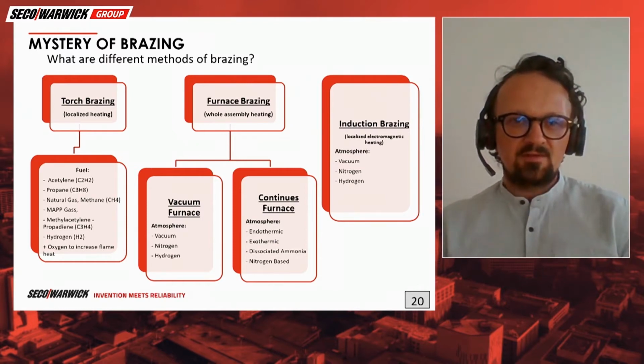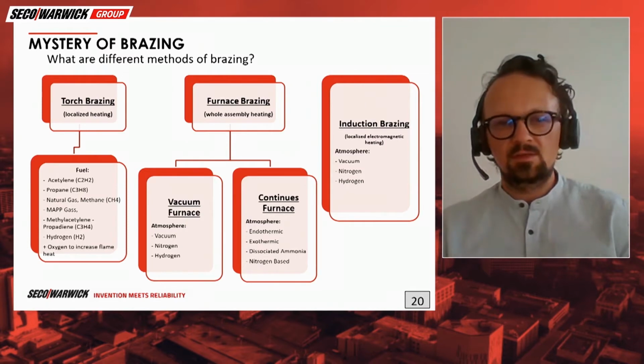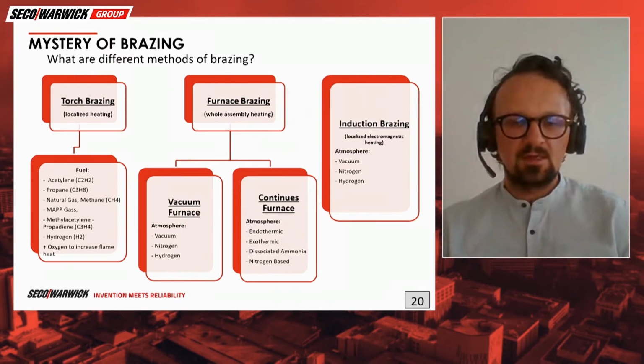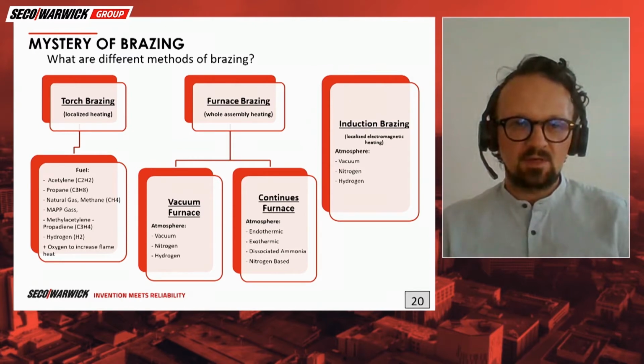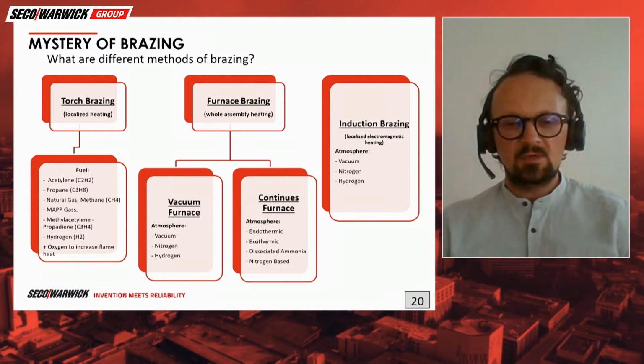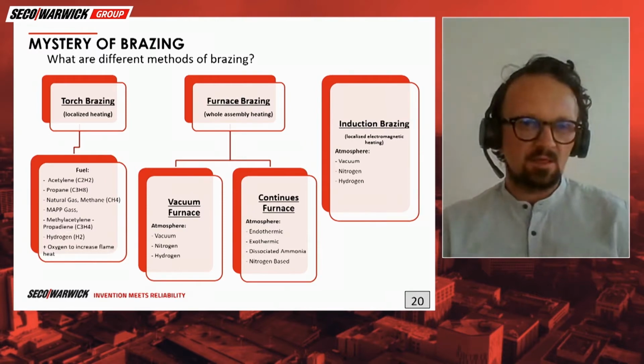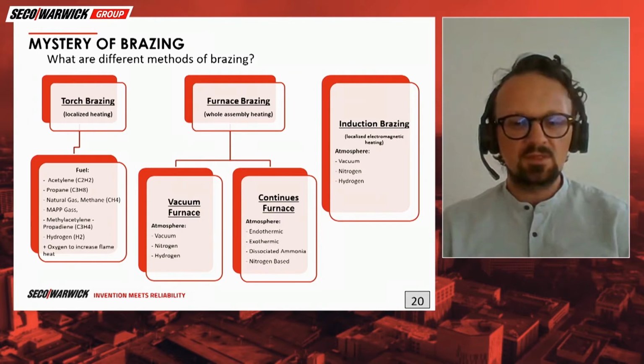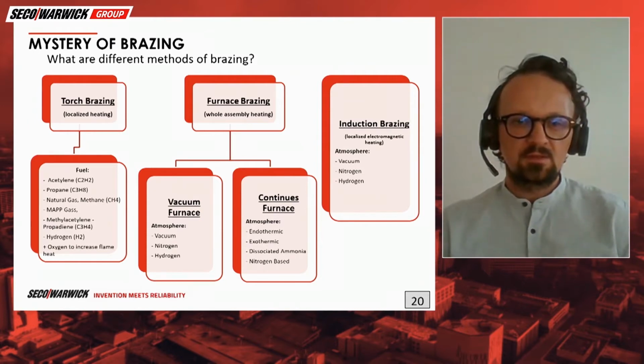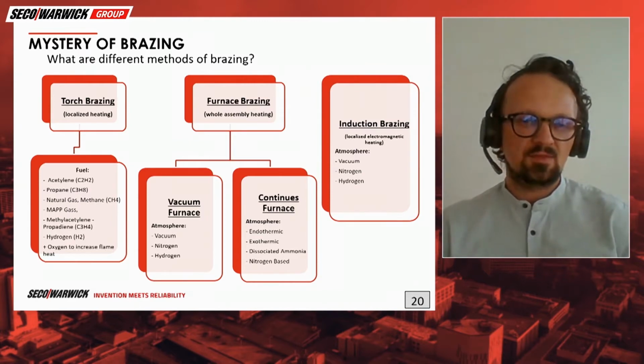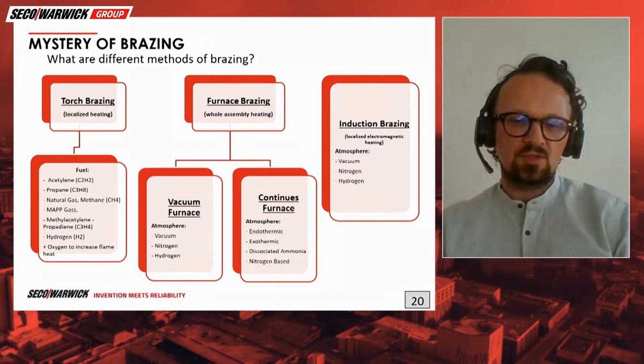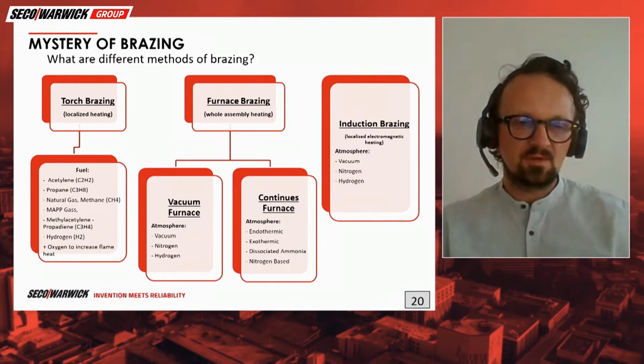Another package is furnace brazing, because we can have vacuum furnaces and continuous belt furnaces. They are a little bit different in how they operate. Both of these types of furnaces use some kind of protective atmospheres. In a vacuum furnace, we have much cleaner atmospheres because we can use vacuum or gases like nitrogen, hydrogen, argon. I forgot about the argon here. But you're starting with a vacuum at the beginning, so the atmospheres you introduce in the vacuum furnace are much cleaner. In a continuous furnace, we can have endothermic, exothermic atmospheres and dissociated ammonia and nitrogen based. Mostly these atmospheres are nitrogen hydrogen based, and some of these atmospheres are not very good for some of the materials.